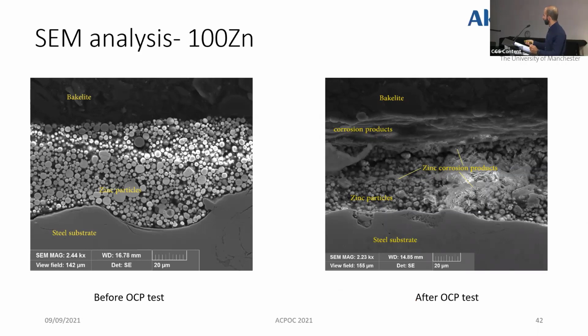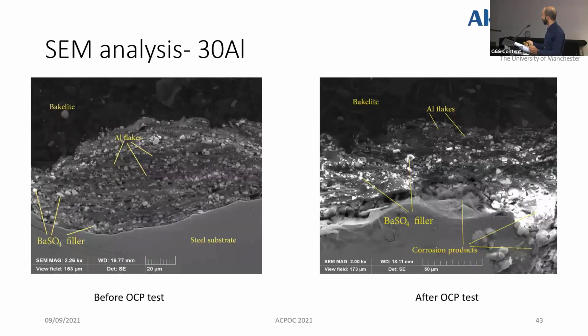So this 100 zinc is fully loaded with zinc particles of different sizes. After the OCP test, you can see these sheets here, which are the simonkolleite corrosion product. And you can see also that many of the zinc particles have not reacted, which is one of the problems associated with zinc corrosion in zinc-rich coatings, that many of the zinc particles remain without any reaction because of the disconnection by zinc corrosion products.